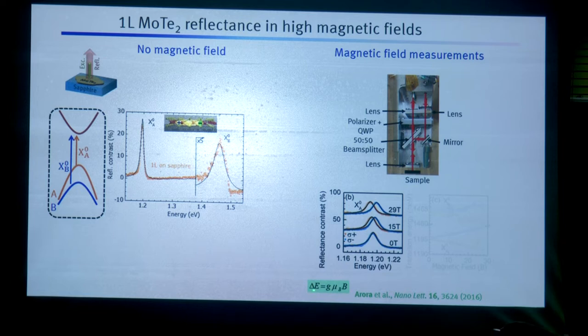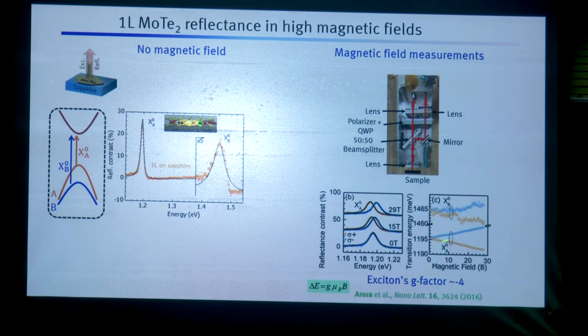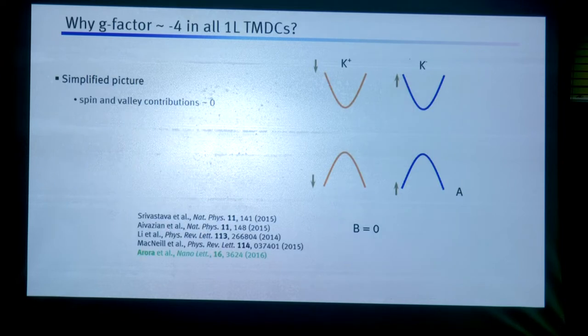And now, if we have ΔE equals g μB B, which is the Zeeman splitting, then the g factor was found to be equal to -4 between these split lines. Now, why -4? The reason is the following. A very hand-waving reason is the following. These are the two valleys again. There are three types of magnetic moments responsible for these Zeeman effects, but only one is dominant.